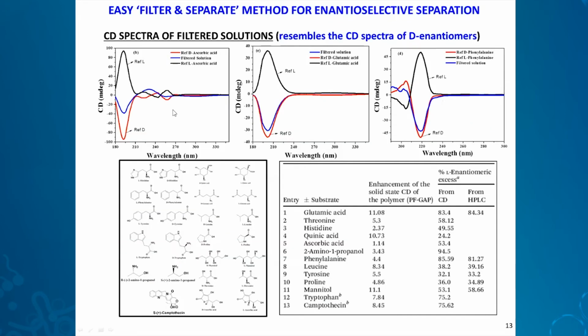So what was found was that this is a reference L molecule. Our polymer is L polymer. You should remember, the remaining solution is richer in D. Why? Because the L enantiomer is selectively taken up by the polymer powder. So the solution becomes richer in D.